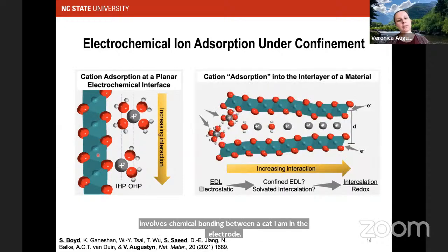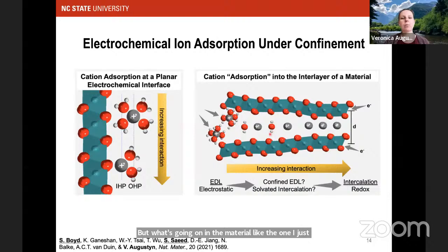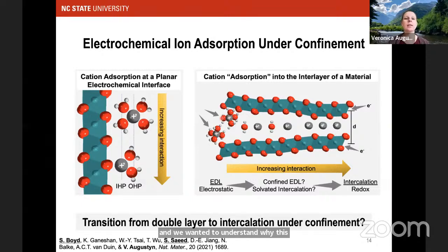But what's going on in a material like the one I just mentioned, where we have water in the interlayer, is that you're now seeing a situation where the electrolyte is not just left cleanly at the outer surface. It's clearly penetrating into the structure. And we wanted to understand why this could be the case in an insertion process. Is there a transition from the double layer to a redox process like intercalation under confinement?